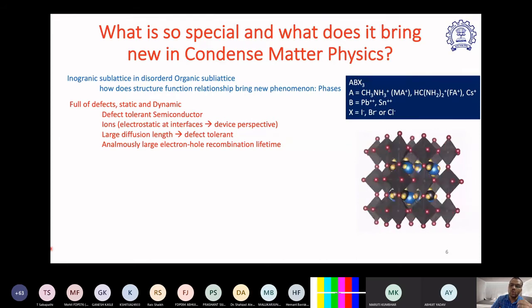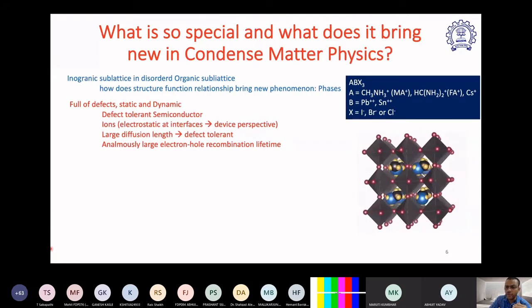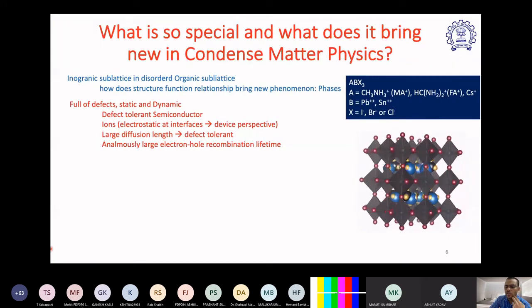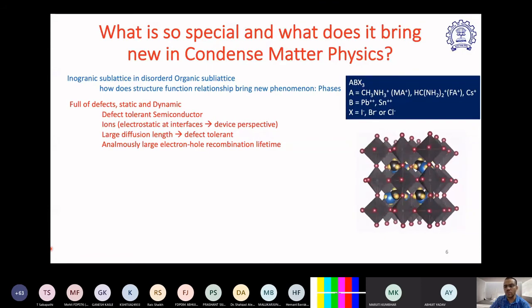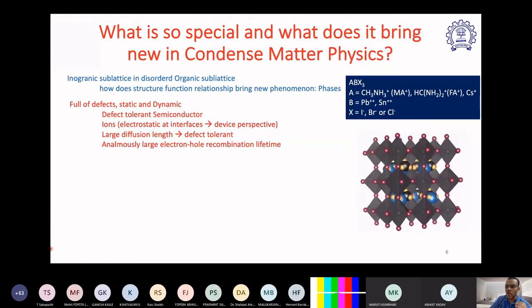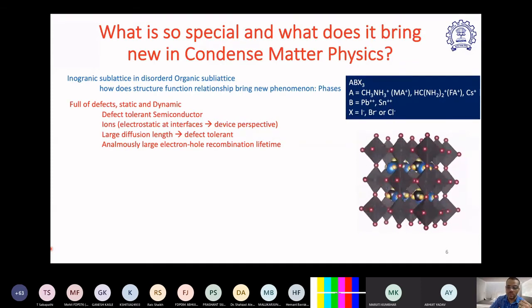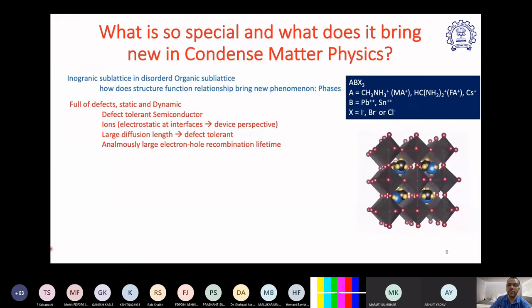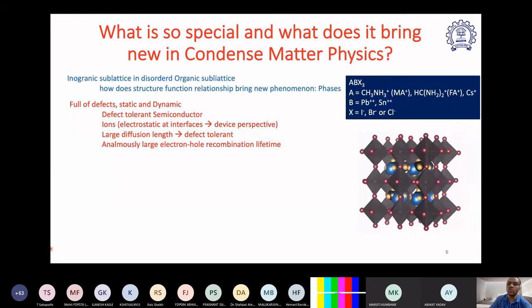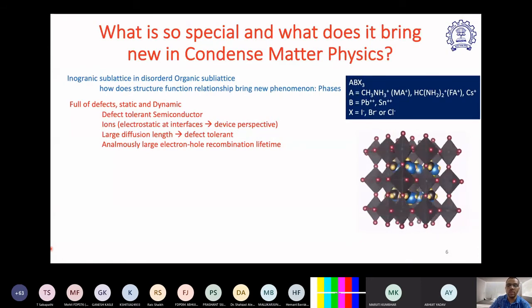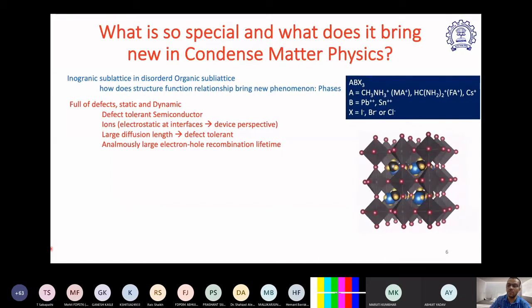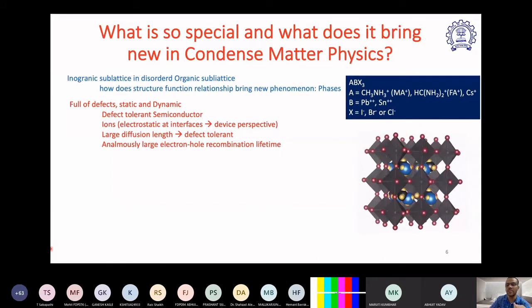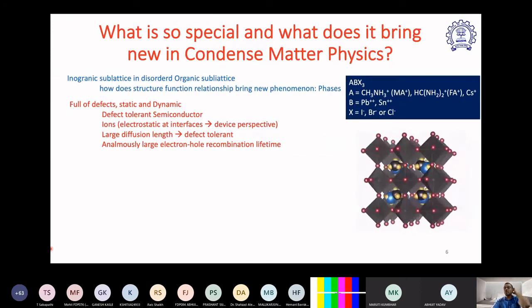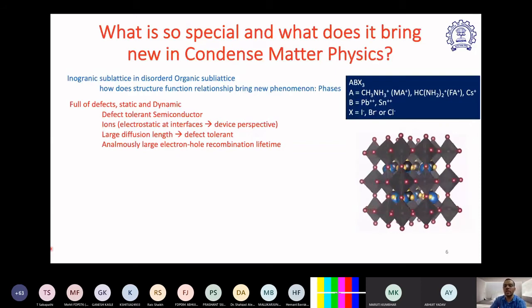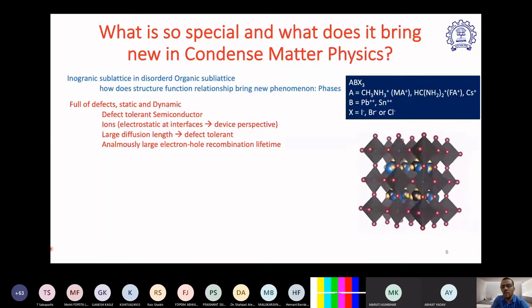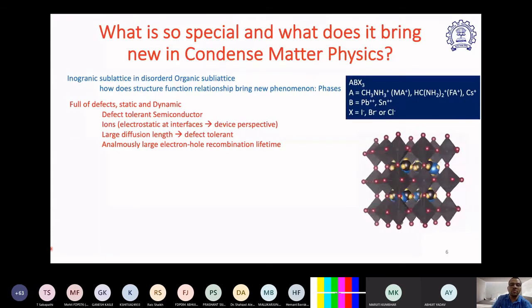However, despite having so many defects, this works fantastic for devices. So what goes wrong in conventional semiconductor physics? A semiconductor full of defects working so nicely in devices, how is that possible? That is the question. And the answer is that this is possible because this semiconductor is defect tolerant. Defects are there, but they do not really make any difference in the device properties, because there are doctors sitting in the same crystal structure, the same lattice, which come and heal the defect immediately whenever there is a requirement. Because of this methylammonium ion which moves around, and even the lead iodide, have very low activation energy.